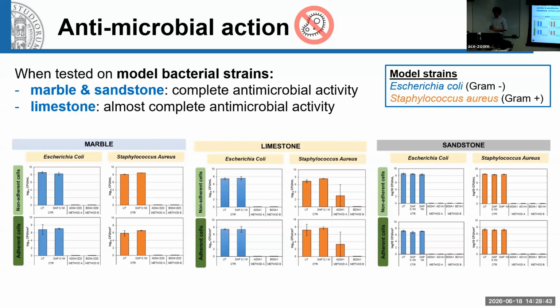Also in this case, we tested the resistance of this antimicrobial ability to accelerated aging by rain, and we found good results, meaning this activity was maintained also after accelerated aging.